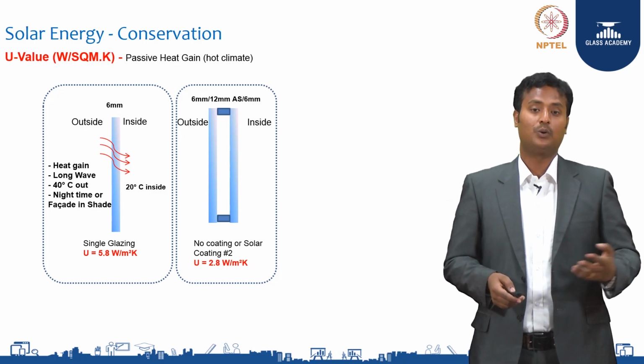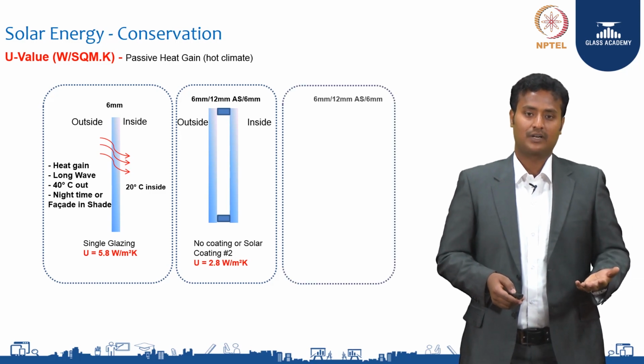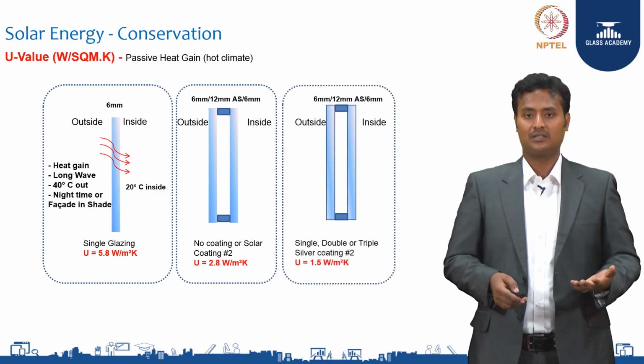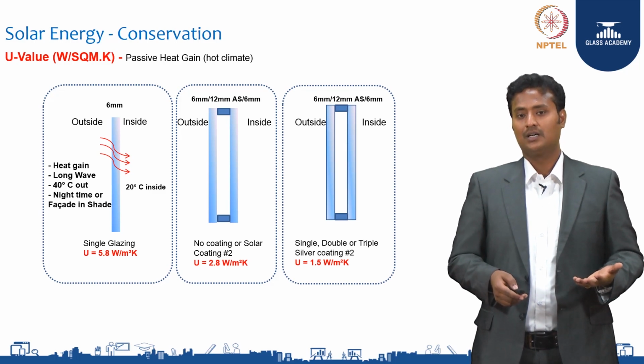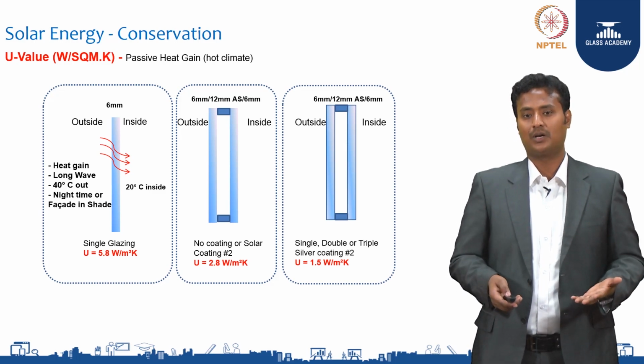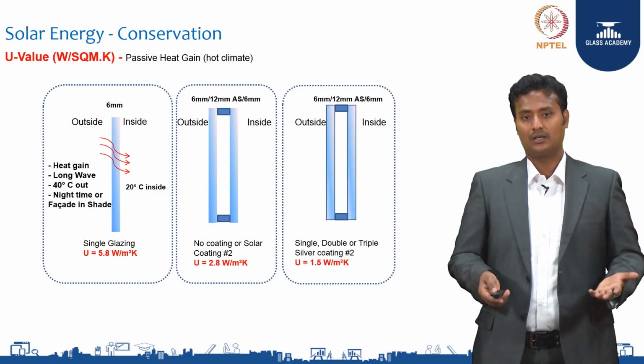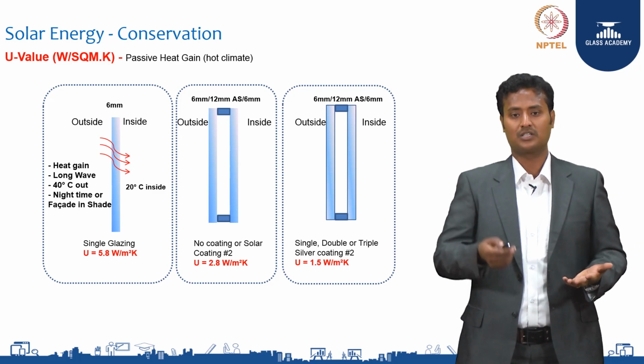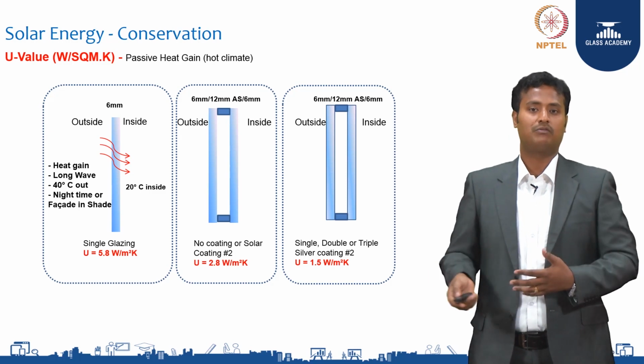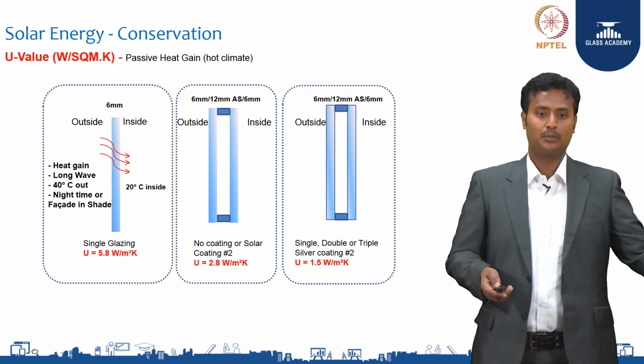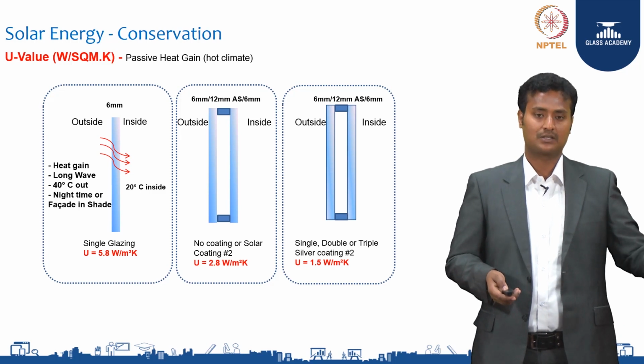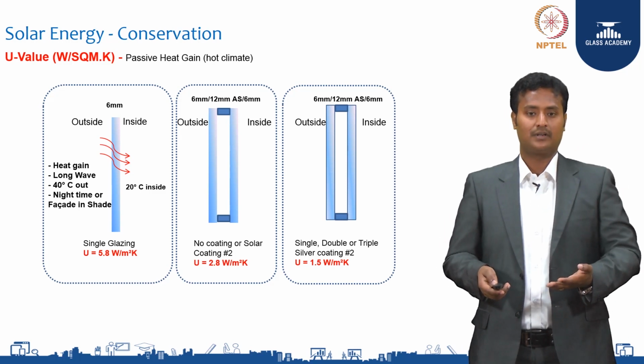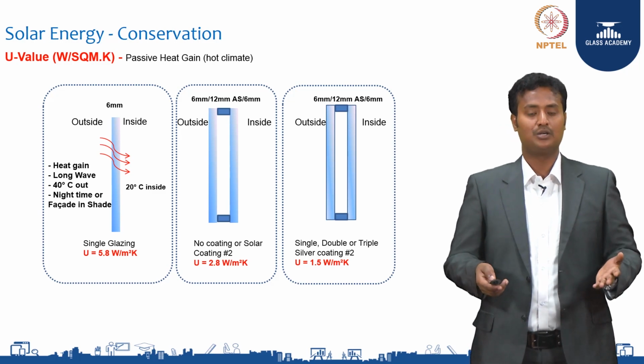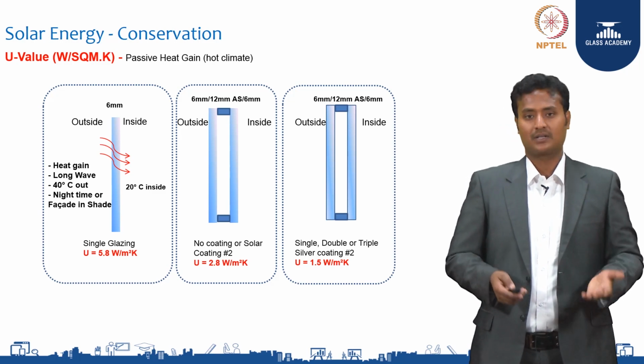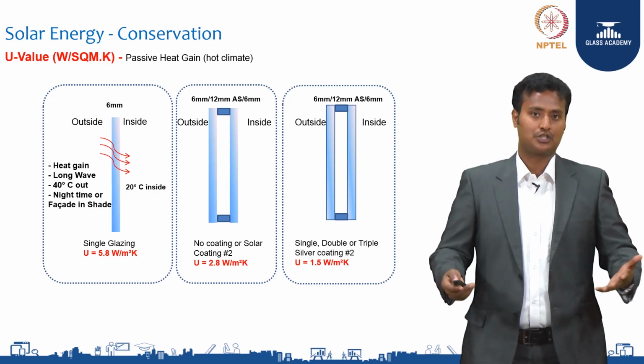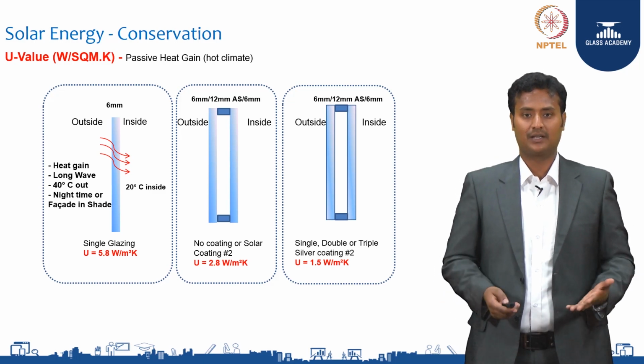Furthermore, you can get a U value reduction. For example, if you use any triple silver or double silver coated glasses, you can get further reductions in U value. The more the U value is reduced, for example to 1.4 watts per meter square Kelvin, the better the performance of the glass. The single pane has 5.8 watts per meter square Kelvin. If you take double silver, for example, the U value of the double glaze unit is going to be 1.5 watts per meter square Kelvin. So thereby you get a profound energy saving.